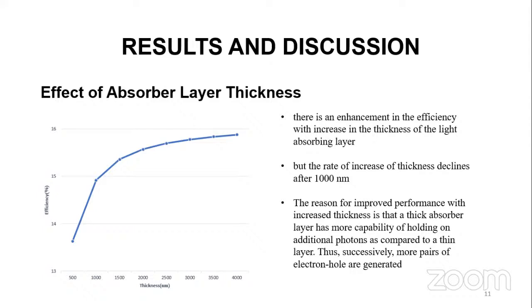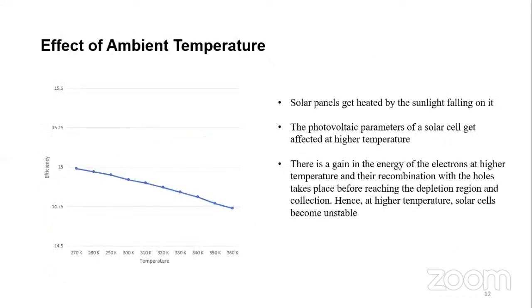In this work, we have studied the effect of absorber layer thickness, and we have seen that there is an enhancement in the efficiency with increase in thickness of the light absorbing material, that is Sb2S3. If we closely observe, the rate of increase declines after 1000 nanometers. So that's why we have optimized the thickness at 1000 nanometers. The main reason for this improved performance can be attributed to the fact that as we increase the thickness, it has more capability of holding additional photons as compared to the thin layer, and successively more pairs of electrons and holes can be generated.